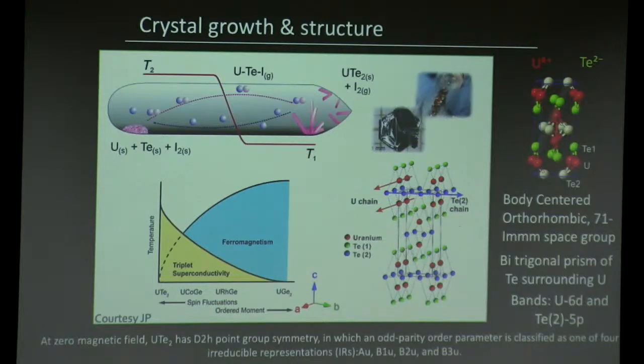Just to give you a sense of the symmetry of the system, as well as the bands close to the Fermi energy, this is a body-centered orthorhombic material with the IMMM space group. The way you visualize this material is: these red balls are the uranium, and the green and whitish ones are tellurium. You can think of it as a trigonal prism of telluriums surrounding a central uranium atom. In each unit cell there are 2 uranium atoms.